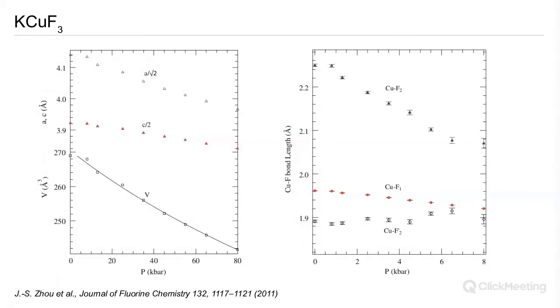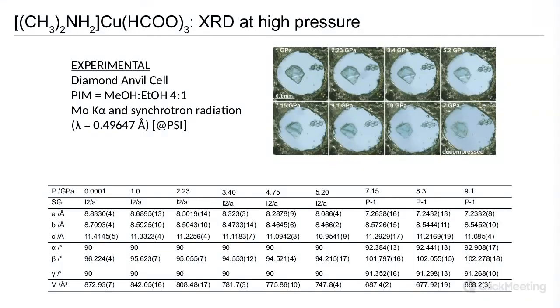So what happens to potassium copper fluoride under high pressure? This is a study from 2011. On the right here, I plot the copper fluoride bond lengths. And what we see, very similar to what Piero mentioned, is that the softer bond, the Jahn-Teller elongated bond, compresses. And it moves down and down and down until it reaches a similar value to that of the equatorial bonds at 8 kilobar. So essentially, we're just suppressing this Jahn-Teller distortion. And what the nature of this orbital state is up at high pressure is an open question. It's something that was raised by a member of the audience. So there's no transition observed. However,